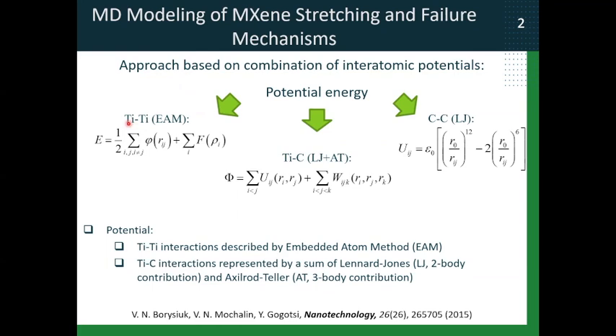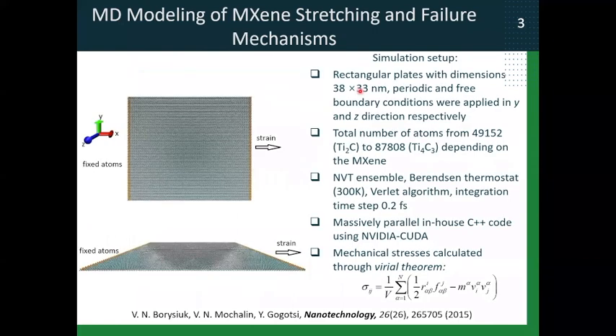So for example, we used embedded atom potential for titanium-titanium interactions. Titanium-carbon interactions we described by a combination of Lennard-Jones and Axilrod-Teller three-body potential. And for carbon-carbon, we used very simple Lennard-Jones potential. So this was our functional for potential energy in MXenes, and this is our simulation setup. We used quite large sheets of MXenes, 38 by 33 nanometers. For simulation, it's quite large because the number of atoms is around 50,000 to 90,000 atoms, depending on which MXene we use. Simulations were done in NVT ensemble, and we used our own in-house written C++ code for this simulation.